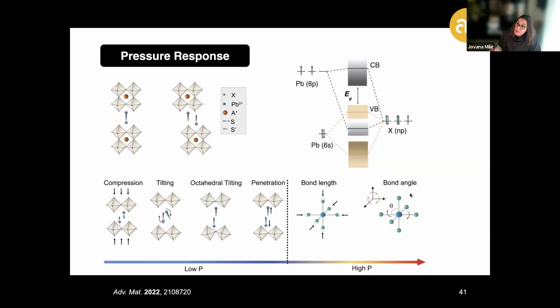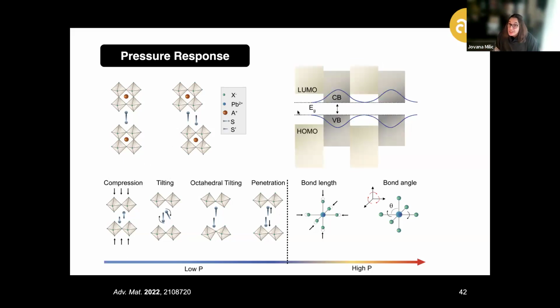So this is where these hybrid systems, including larger organic components like layered hybrid perovskites, might provide the opportunity to rely on some of these additional degrees of freedom in softer materials to reduce the pressure ranges, which we can access some of these changes through additional reorganizations within the spacer layer, for example through their different penetration into the inorganic layer, different octahedral tilting, or rearrangements directly within the organic layer as a result of the compression that would then directly be reflected in the resulting optoelectronic characteristics of the layered hybrid material as well.